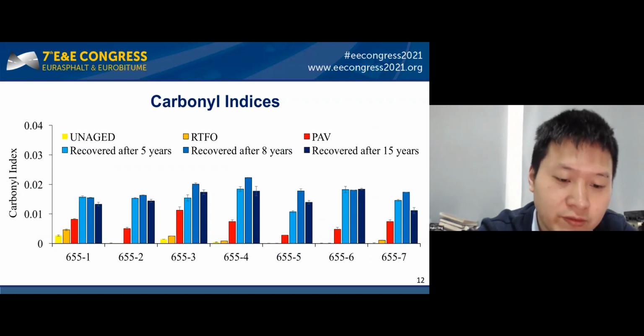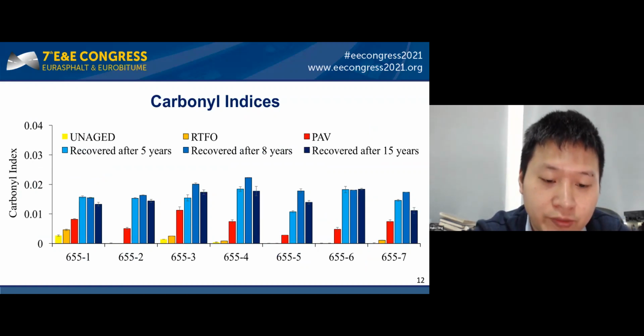FTIR analysis of the lab-aged and the recovered binders confirmed once more that the PAV residue is not aged sufficiently. It would likely be better to age for 14 hours or even longer and in thinner films, as we have published at a past Eurobitume Congress in Istanbul. Aging for 14 hours brings the level close to what is obtained for 8 years of service.